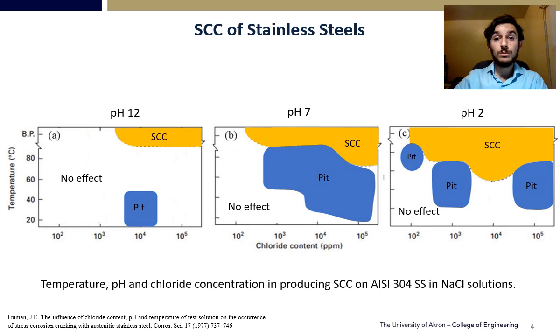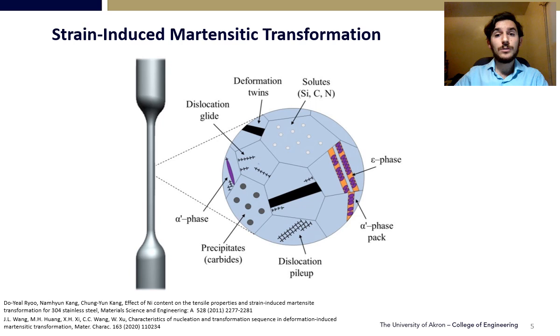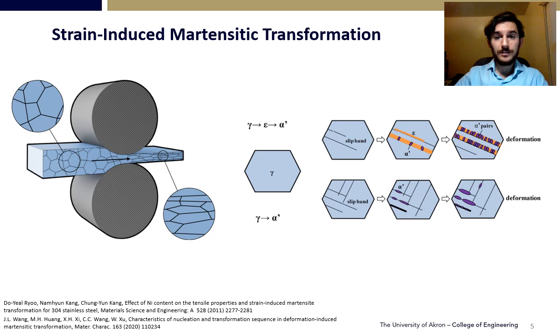It is because of the strain-induced martensite that the reinforcement would suffer from SCC and fail. The strain-induced martensite is one of the strain-hardening mechanisms that improves the mechanical properties of the alloy. Austenitic stainless steel can undergo phase transformation if subjected to cold work, changing the austenitic grain to the strain-induced martensite — starting from austenite to slip bands, then epsilon, and finally alpha-prime.